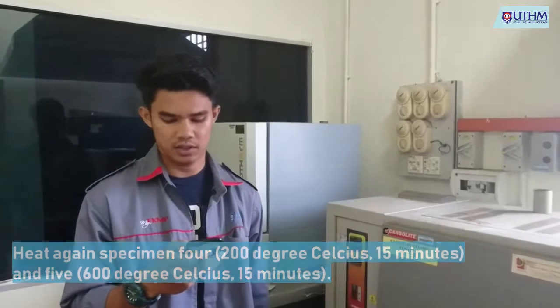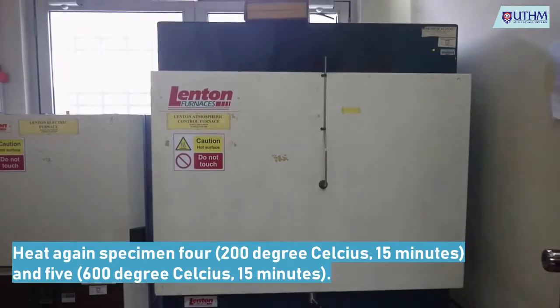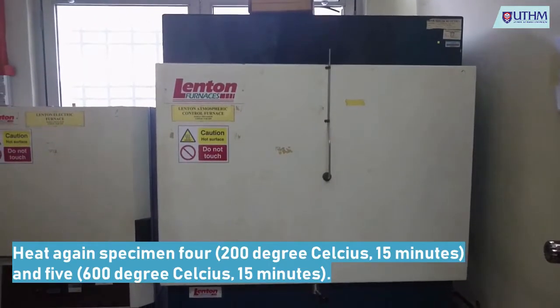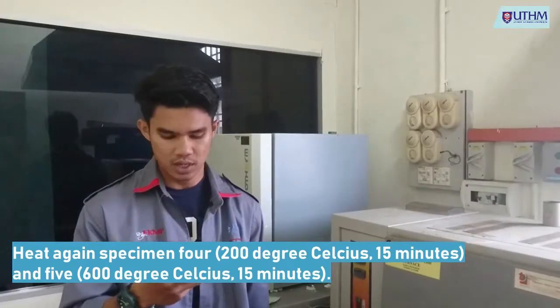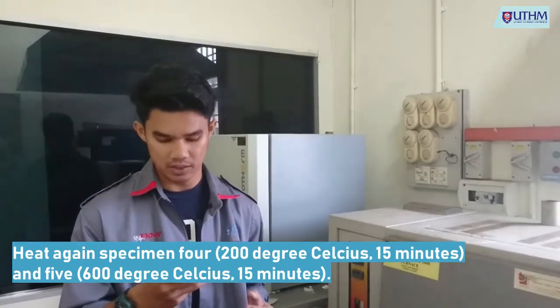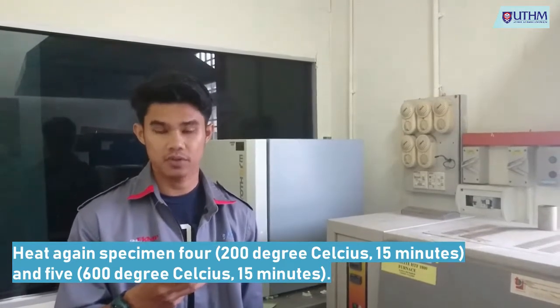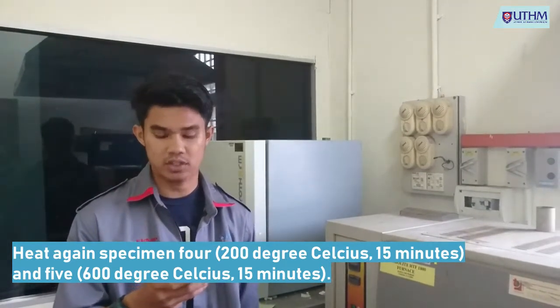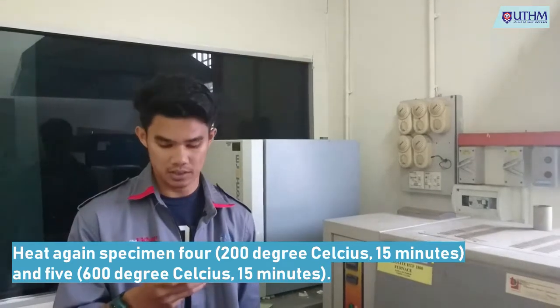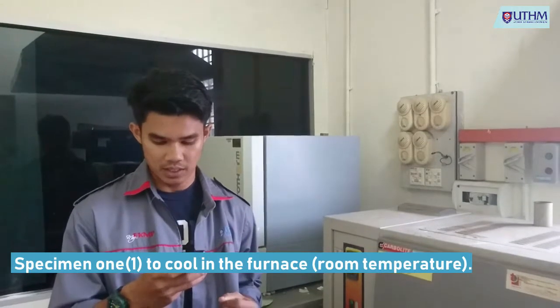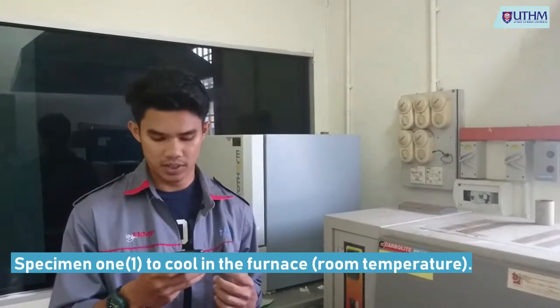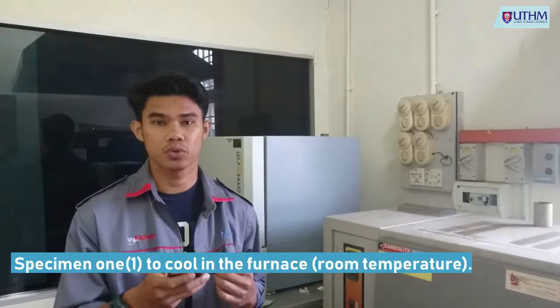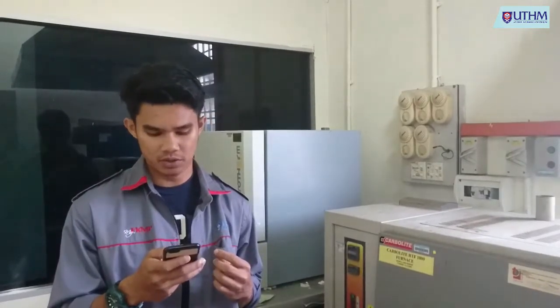After that, heat again specimens 4 and 5. Heat specimen 4 to 200 degrees Celsius and allow it to stay at this temperature for 15 minutes. But heat specimen 5 to 600 degrees C and allow it to stay at this temperature for 15 minutes. Turn off the furnace, leaving specimen 1 inside the furnace. Allow specimen 1 to cool to room temperature. Lastly, keep all specimens for the sample preparation and metallography experiment.